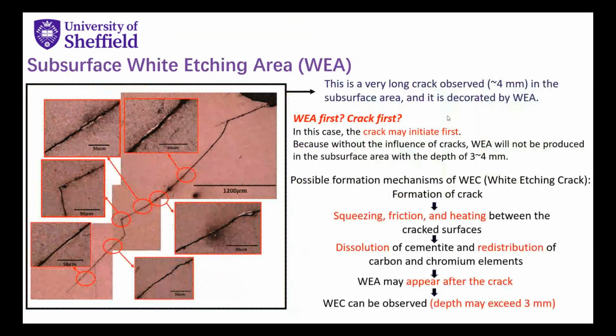And also, we can observe some white etching areas of these cracks. As you can see on the left-hand side is a very long white etching crack, WEC, observed in the subsurface area. And you can see many WEAs can be observed near the cracks.